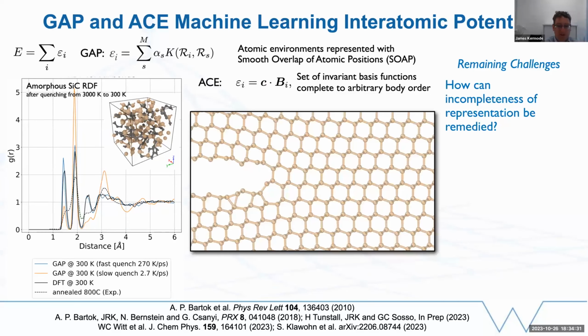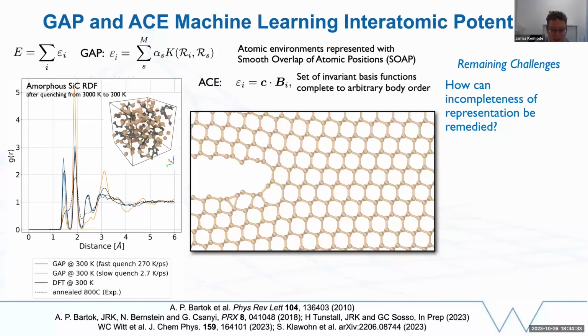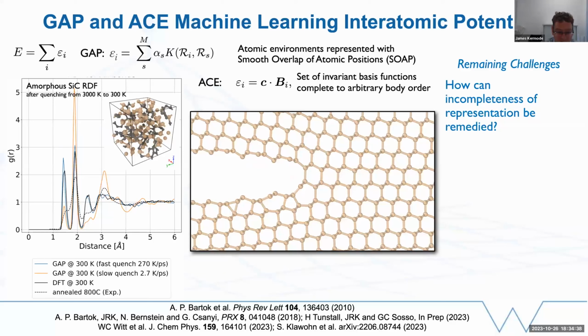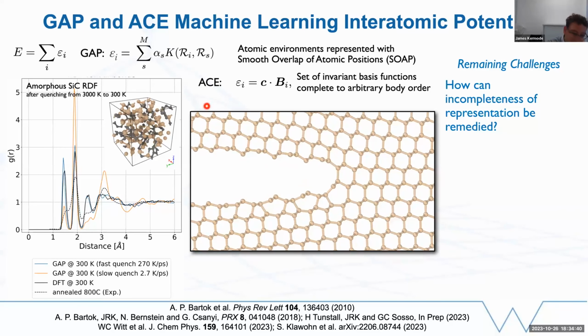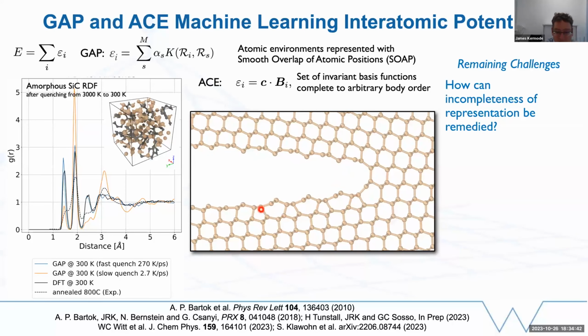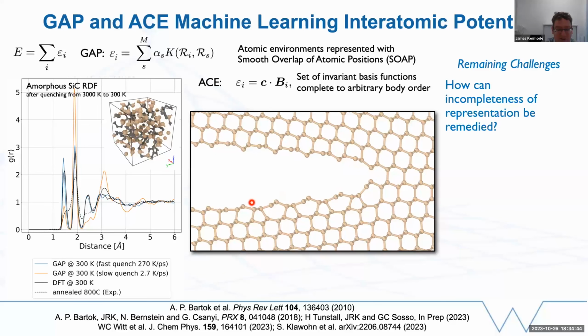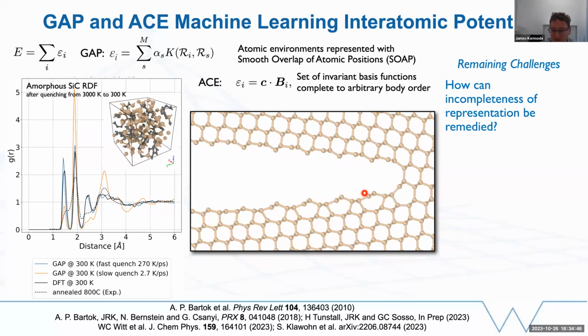So if I return to the fracture example, if I take that ACE model and apply it to the fracture of silicon that I showed you earlier on, that's actually quite well described on this model. We see the same surface reconstruction that I showed you before, the alternating pentagons and heptagons. So we're capturing electronic structure effects within the model without having to include them explicitly, and we're getting a good description of the fracture process. This was a quasi-static simulation rather than the molecular dynamics one I showed earlier on, and that explains why it looks a little bit more jerky, but it's really doing a pretty good job.